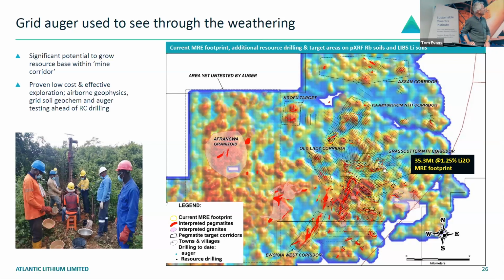So you can see we highlight an area of coincident geochem and geophysics and then go into that area and map. And if we identify outcropping spodumene, it really prioritizes that target. Otherwise, it's just a grid auger drilling pattern. So this is like a corridor of anomalous results, as is this area here. And this anomaly here, which is the Krofu target, has lithium mineralization.